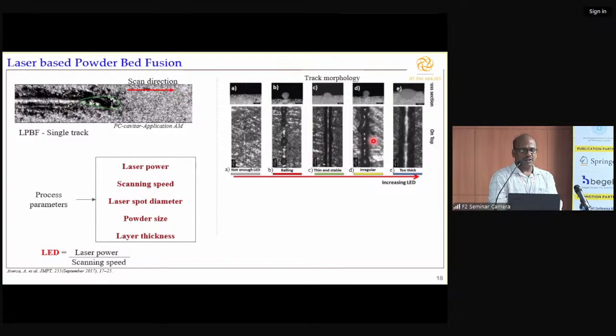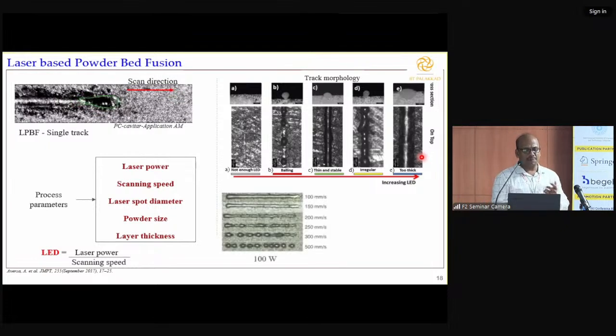If the laser energy density goes a little more, it gives an irregular shape. And finally, I get a thick one. So this third one, that means C, is thin and stable, and the last one is too thick, more or less good. But the problem is when I need an accurate track, I need thin and stable, not a thick one. So you have to make this decision first. Once it is done, when I'm seeing from the top, the track is continuous, thin, and we are able to make the required dimension. But how about the bonding? That plays an important role.